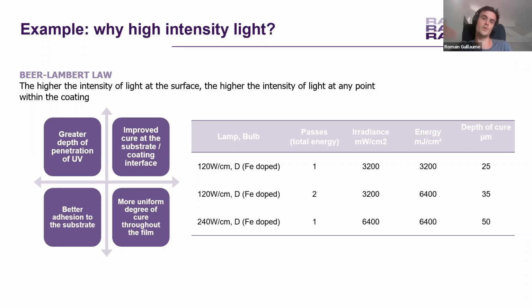Now let's say I want to increase my energy, so I go 2 times under my 120 watt per centimeter lamp. So with the same irradiance, but going 2 times below it, I have an energy which is doubled compared to the first line. I have an energy of 6,400 millijoule per square centimeter. And with this energy, I'm able to increase a little bit the depth of cure of my formulation up to 35 micrometers.